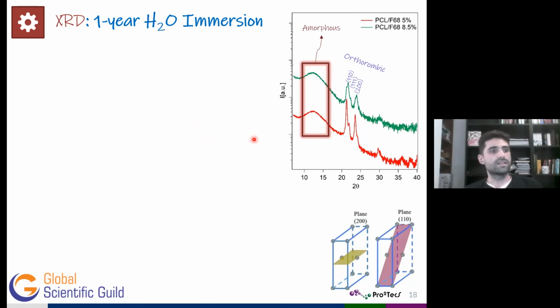Okay, finally, and just not to extend too much, because we are almost at the end of the webinar, we also apply XRD tests over the systems after water immersion. And we corroborated again the same orthorhombic structure in all these cases. But more importantly, after water immersion, we confirm the lower crystallinity degree as we saw in the DSC results. But not only that, we also obtain a higher mesophase content as a consequence of the release of the pluronic into water.